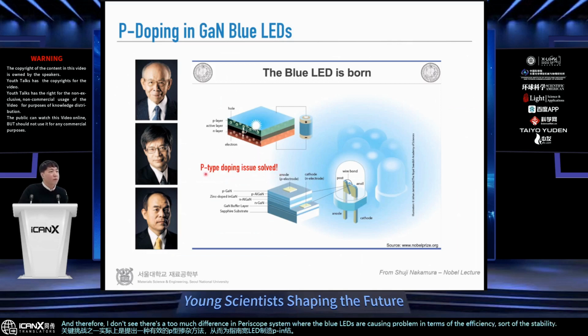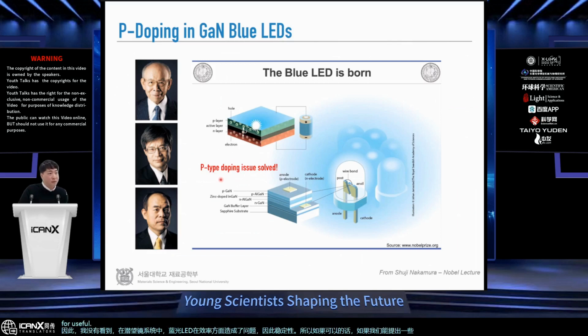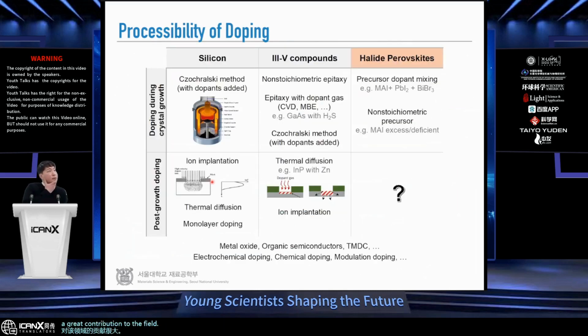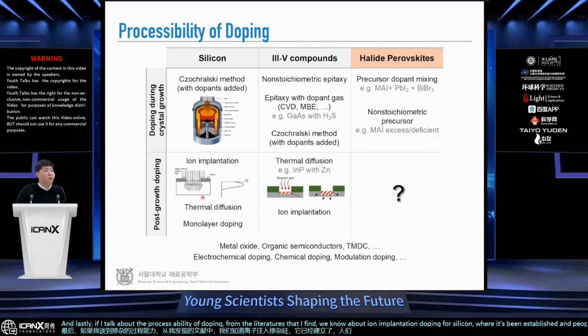So if we can come up with some efficient p-type doping method for useful device applications, then that would also be a great contribution to the field. And lastly, if I talk about the processability of doping, from the literature that I find, we know about ion implantation doping for silicon, where it's been established and people use it all the time, where you first use the thermal diffusion of these ions, and also then you accelerate these ions by electric field in order to spatially target where your ion dopants will be.